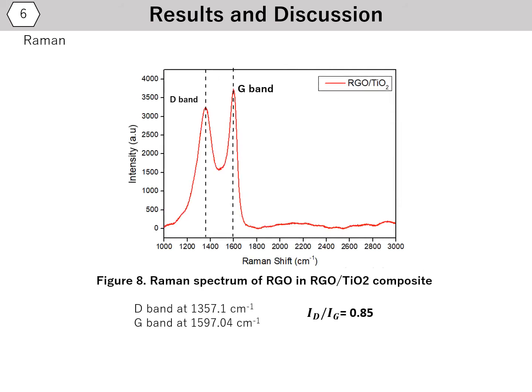Here we show Raman spectra of RGO and RGO titanium dioxide composite. In Raman spectrum, we found that G-band has higher intensity than D-band, with the ratio of D-band and G-band about 0.85. It indicates that RGO and RGO titanium dioxide composite may possess low defect density and result in good quality of RGO. However, for counter electrode application, defect in graphene or RGO plays a role in catalytic activity for reducing iodide triiodide ion in dye regeneration.